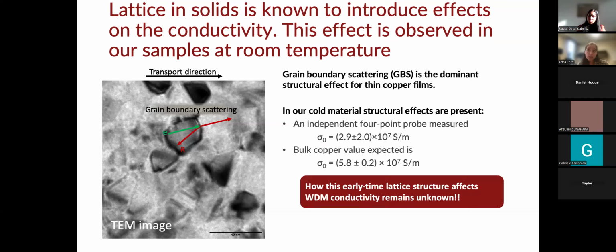Well, the main reason is because in really thin films, when you're going to a nanometer scale film, your system will actually be composed of many little crystals that are attached one to another one. You won't have a main bulk system as if you had thrown just melted copper into a bucket and let it crystallize by itself. So in this case, you can see here a TEM image of our copper films, and you can see these small grains that are around the size of 10 nanometers.